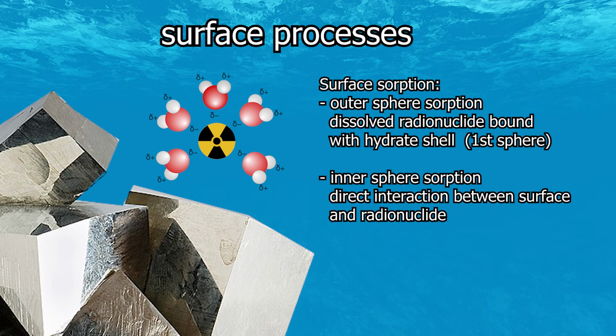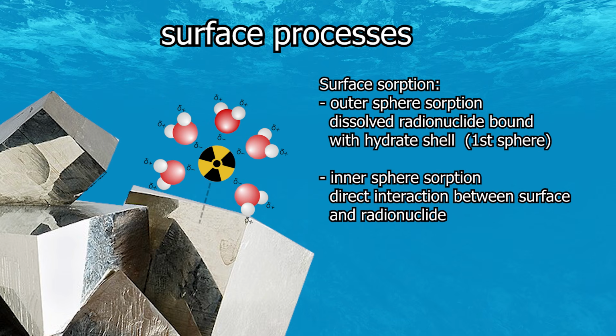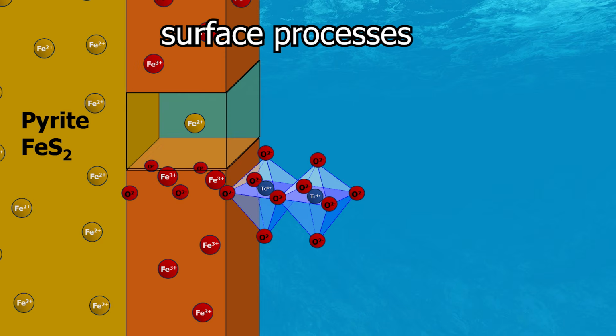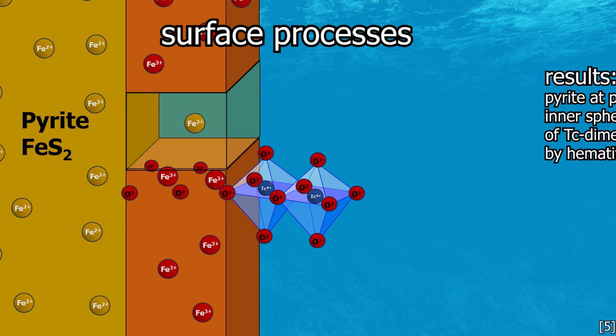If at least one part of the hydrate shell is removed, a chemical bond may form between the components of the mineral and the radionuclide itself. This is then referred to as an inner sphere complex. This could also be measured here. In this case, sorption of technetium dimers by oxide parts of the iron oxide was demonstrated.